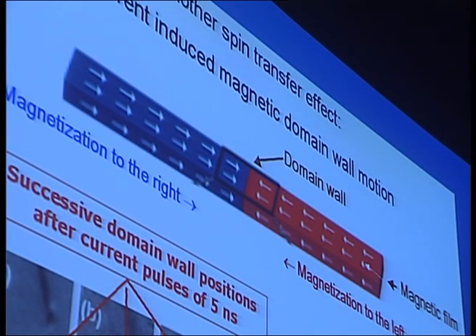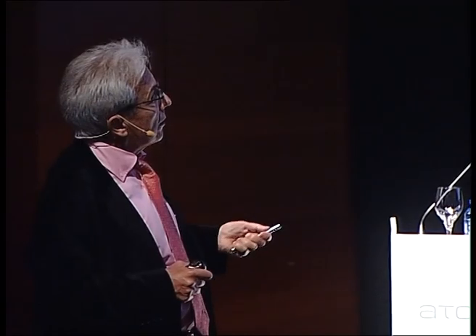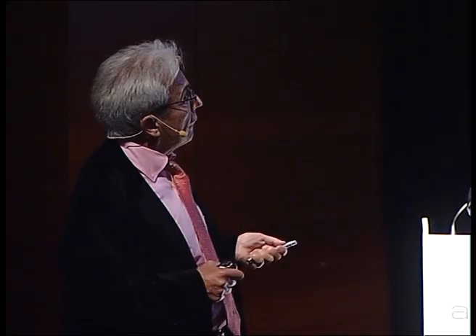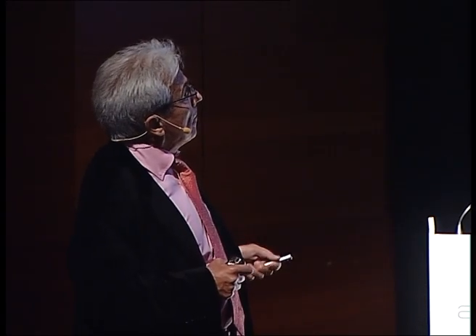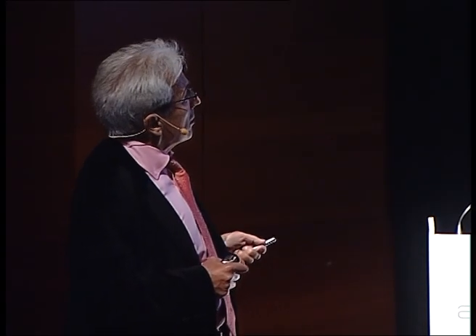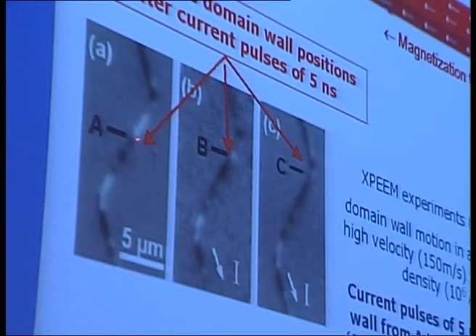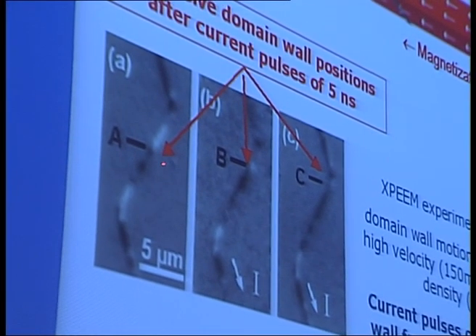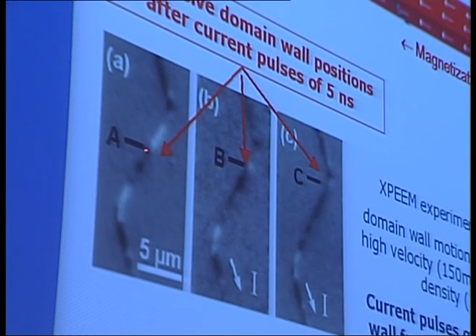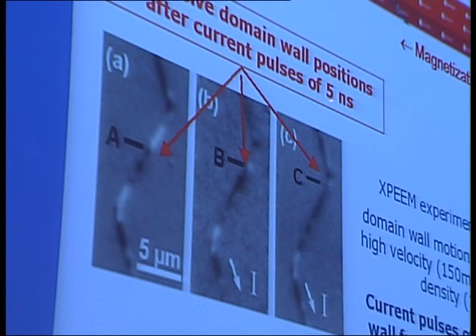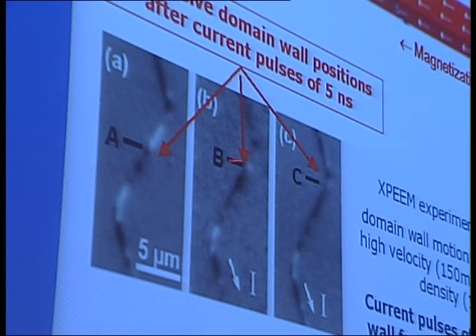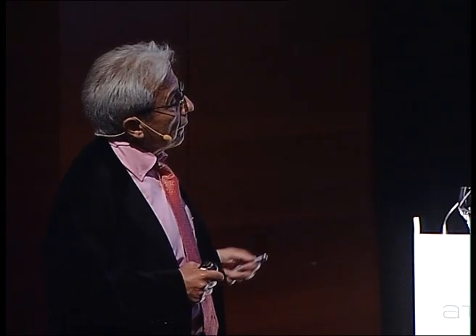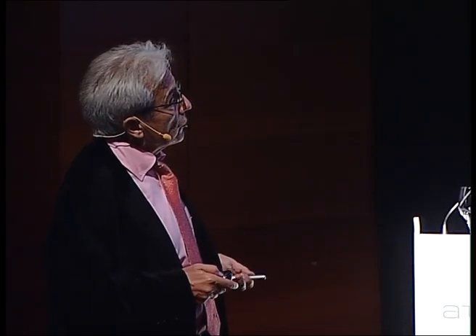An experimental example, this is a nanowire. You see the scale 5 microns, and the image, I don't explain the techniques, the domain wall is the frontier between dark and white. And you can see by sending small pulses of current of 5 nanoseconds, it's possible to move progressively the wall from this position to this one and to this one. So this is an interesting effect to move the magnetization.